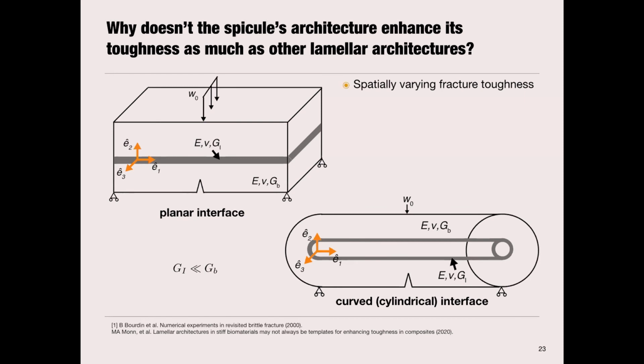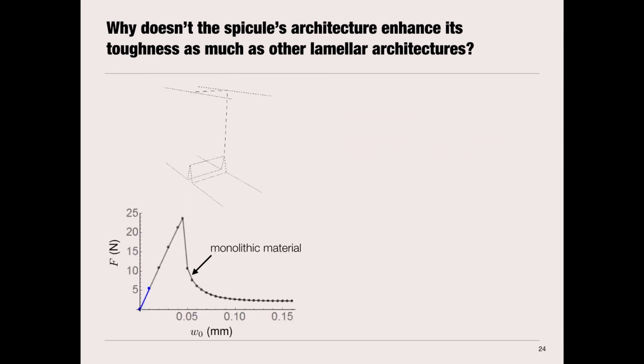The only thing that changes in these materials is not constitutive behavior, just fracture toughness. So we specified an interfacial fracture toughness GI, much less than the bulk material, in a very thin interface, a cylindrical shaped interface and a planar, flat interface. By spatially varying fracture toughness with the same elastic properties, using a regularized variational fracture method, or a phase field fracture method modeled after Blaise Bourdin's work, we looked at the response of these two model systems.